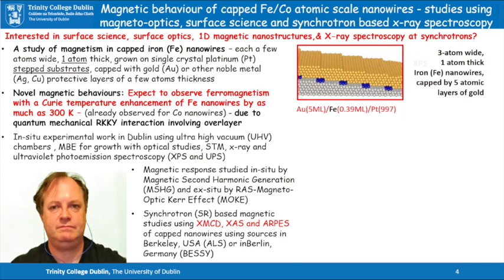The second project I'd like to interest people in is, if you're interested in surface science, one-dimensional nanostructures, magnetism, and X-ray spectroscopy at synchrotrons, then this project may be for you. This will be studying magnetism in capped iron nanowires, just a few atoms wide, 1 atom thick, grown on a variety of single crystal platinum stepped or vicinal surfaces, which are then capped with gold or other noble metals, protective layers of a few atoms thickness. In the diagram on the right is a schematic of a platinum surface with a 3 atom wide iron wire, which self-assembles at the step edges of these stepped crystals, which is then capped with a gold overlay.